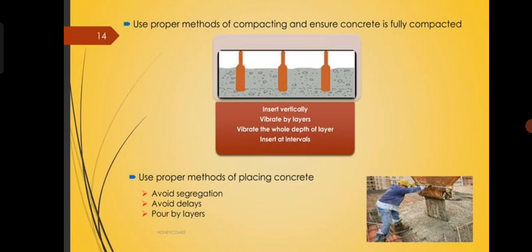Use proper methods of placing concrete. Avoid segregation. Avoid lateral movement. Pour by layers. Insert the vibrator vertically. Vibrate by layers. Vibrate the whole depth of the layer. And insert at regular intervals.